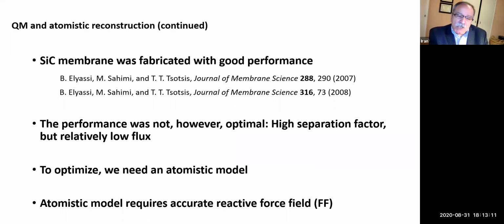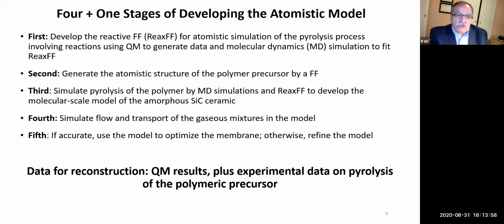So we want to reconstruct the model. Basically, we wanted to mimic the process that we do in the lab. In the lab, we made the membrane, and it was published in a couple of papers about a decade ago. It was a very good membrane in the sense that it had a very high separation factor. However, the flux was low, and therefore we wanted to optimize it. In order to optimize it, since the pores are too small and the hydrogen and other gases interact with the pore walls, we needed an atomistic model. An atomistic model requires an accurate force field, except that this force field has to be reactive, because during the pyrolysis, a lot of bonds break, and then eventually silicon and carbon react with each other, and almost all force fields cannot simulate reaction. Therefore, we had to do this in stages.